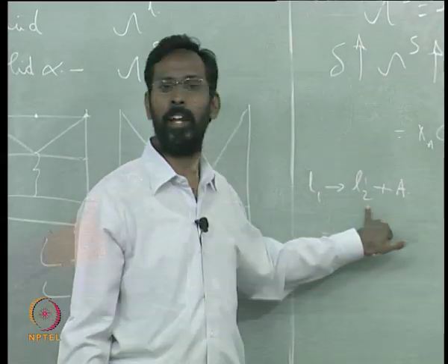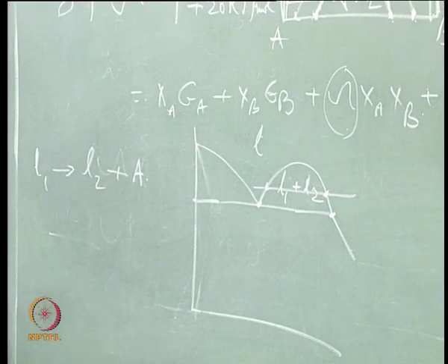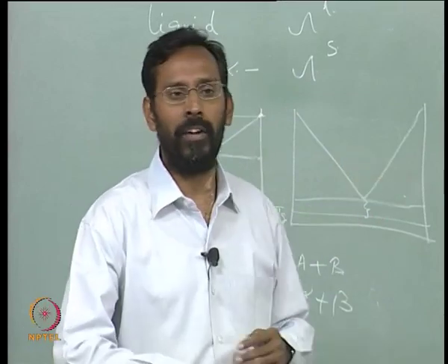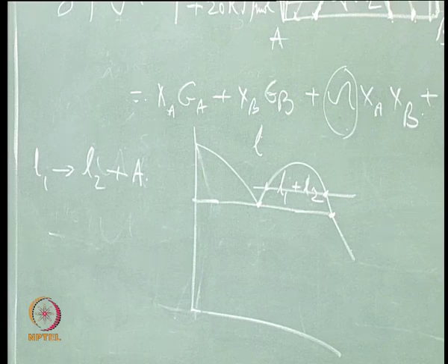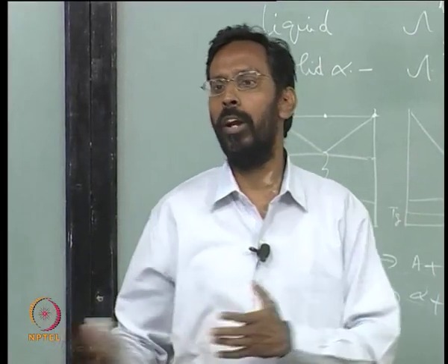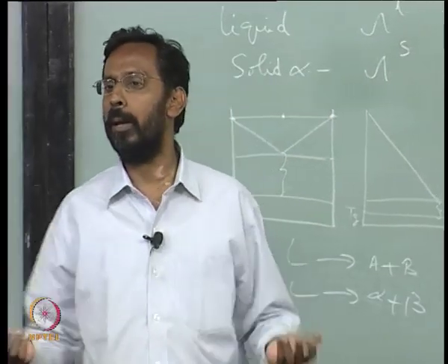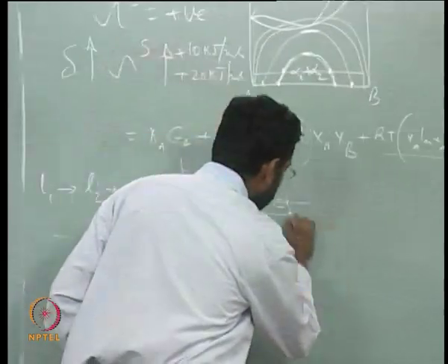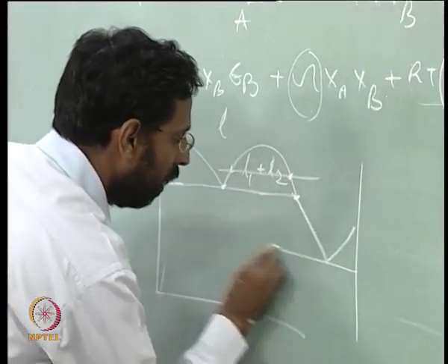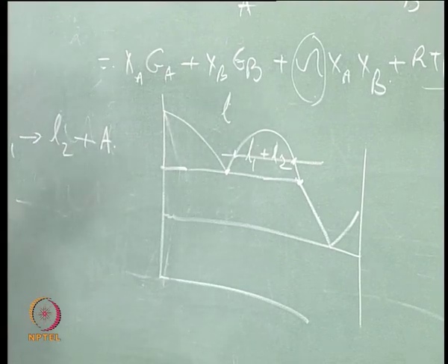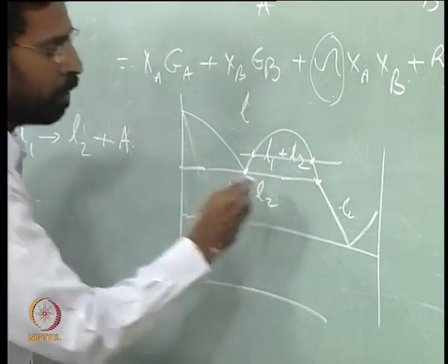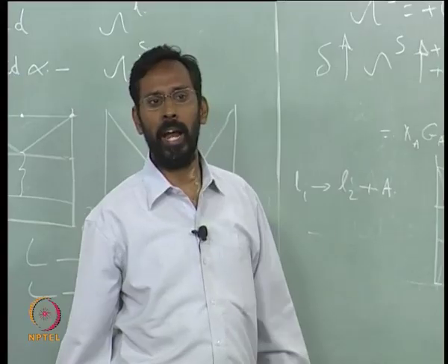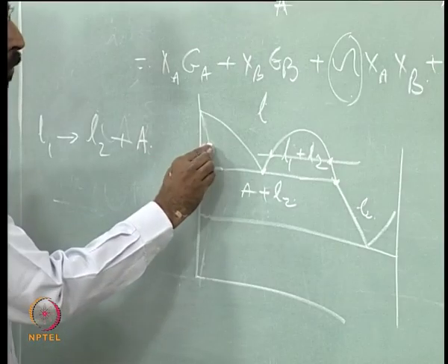and because below the monotectic there is a liquid that is available, because one liquid is giving you another liquid, this liquid which is coming out of the monotectic has somehow to solidify. So, as a result, in many monotectic phase diagrams you would see, in addition to a monotectic reaction, another additional reaction where the liquid which comes out of the monotectic solidifies by either a eutectic reaction or a peritectic reaction. So, you would see here an extension of it, either a eutectic reaction. That means here the L2 that is coming out. So, here you can say it is A plus L2 below the monotectic reaction.